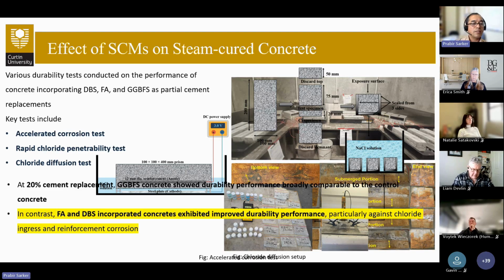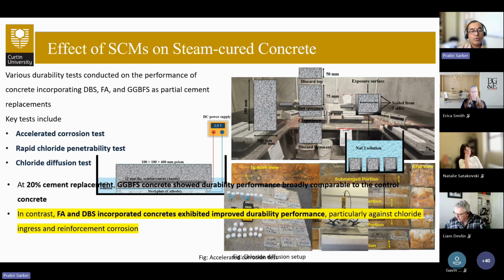So what results were found, basically very briefly. We have not shown all the results here, but the detailed results can be found in some of our publications which are publicly available. What was found is that fly ash and DBS were more effective compared to GGBFS at this 20% replacement against chloride ingress and reinforcement corrosion, from these accelerated corrosion tests.